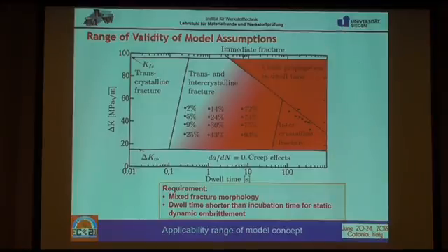And what we have to consider here is that our model is only applicable from a physical point of view if we assume a mixed fracture morphology, and the dwell time, which normally leads to a static dynamic embrittlement under sustained loading, must of course be longer, and you see here the black dots, these dwell times must be longer than the dwell times we applied in our tests in order to keep this model valid. So we have to stay in this range, but this is for technical applications a very useful range.